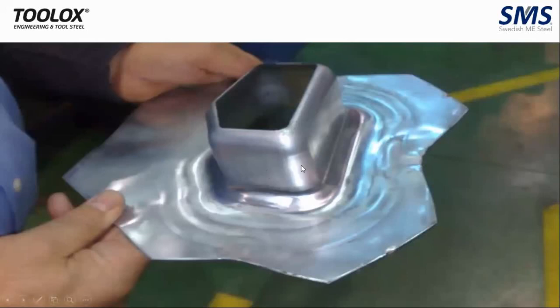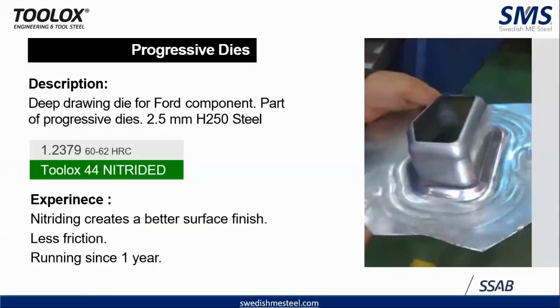So this is the area where you often face the issue of fatigue cracks. It's a deep drawing die for a Ford component, part of progressive dies, 2.5 mm H250 steel. And D2 at 62 HRC was used, replaced by Toolox 44 plus nitriding. It has a better surface finish and less friction.